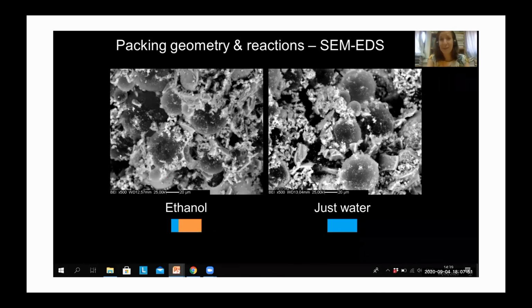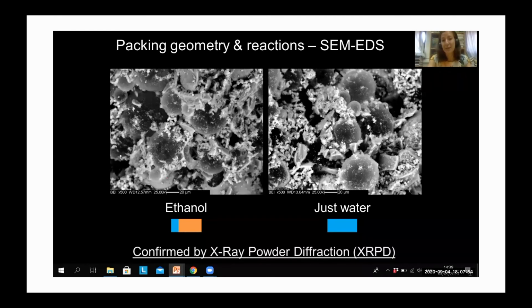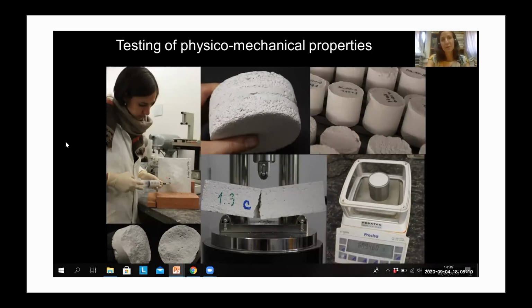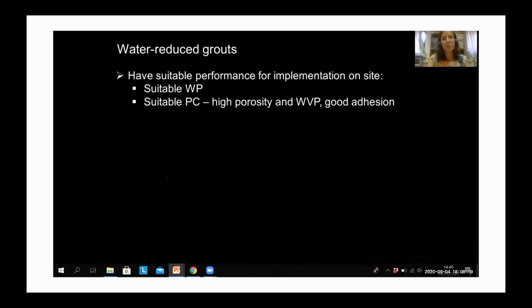are very similar. And this was actually confirmed by X-ray powder diffraction, which gives information about mineralogical phases indeed found in materials. And as you can see, there is a very good packing geometry and density for both. So there was a lot of testing of physical mechanical properties. I'm not going to talk about this today, because that would be too much. But what's the outcome? That water-reduced grout have suitable performance for implementation on site, both working properties and performance characteristics, a very high porosity and good adhesion.